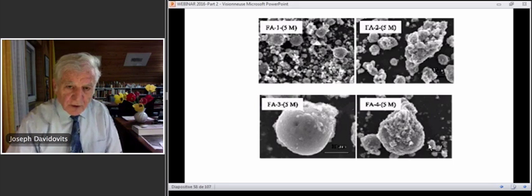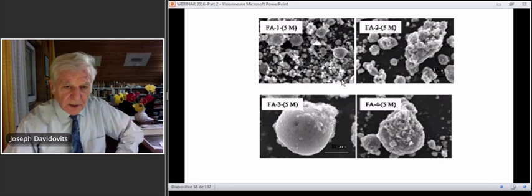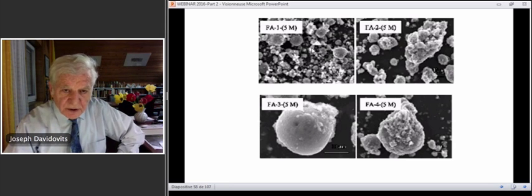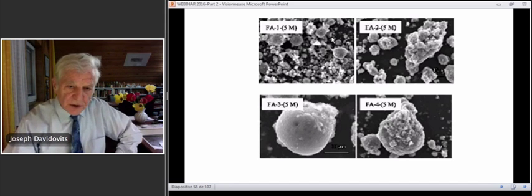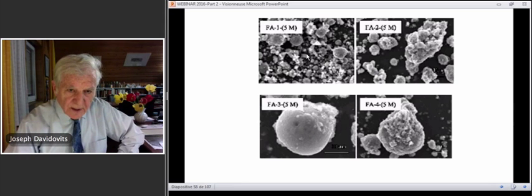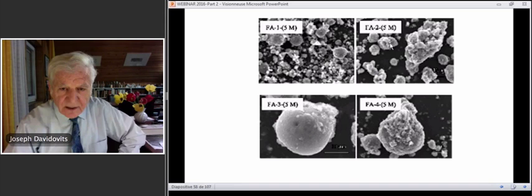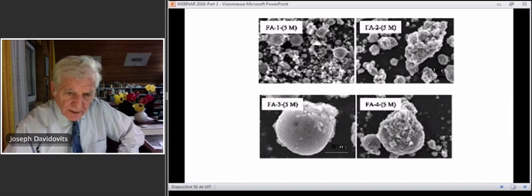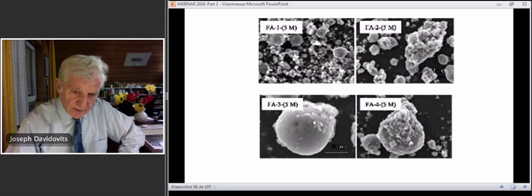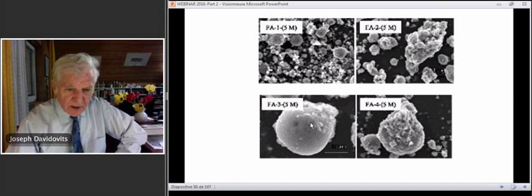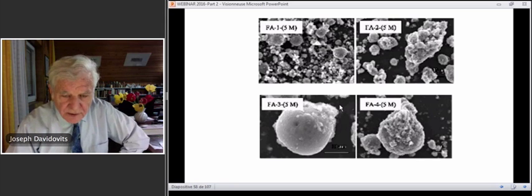And if you look under the electron microscope at what is going on, you have here 4 different fly ashes, and you have the spheres, they are intact, there is no matrix in between. The NaOH solution is surrounding the fly ashes and starts to attack the spheres to disaggregate the spheres on the surface, and what is disaggregated, depolymerized or dissolved will then make the matrix.